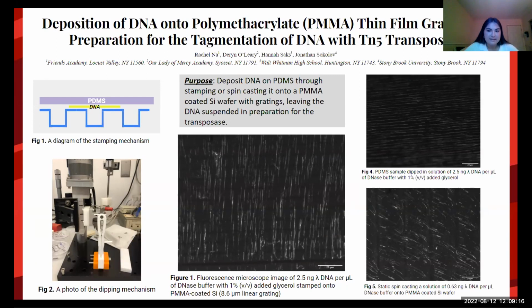Therefore, our group hypothesized that DNA can be deposited onto flat polydimethylsiloxane or PDMS samples and then stamped onto silicon wafers with gratings to leave the DNA suspended across the troughs of the grating, which is called bridging, and also provide steric clearance for the transposases to simultaneously cut and label the DNA strands. We have also explored the idea of spin casting the DNA onto the gratings to achieve a similar goal. This method will allow for larger base pairs of DNA to be labeled and analyzed quickly with minimal risk of losing important genome information and spatial organization.